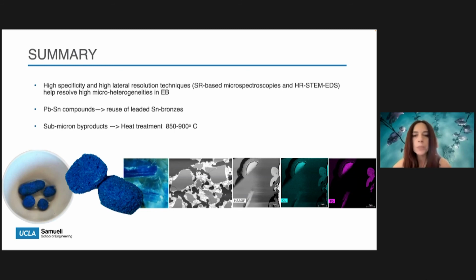Similarly, the abundant presence of sodium silicate as a byproduct from the sintering process of Egyptian blue suggests a heat treatment of around 850 degrees Celsius. So it seems while we have conducted so many analyses on Egyptian blue, there is more to learn. The more and the deeper we dig into its structure, while we may get some answers, more questions are raised regarding its technology and production processes.